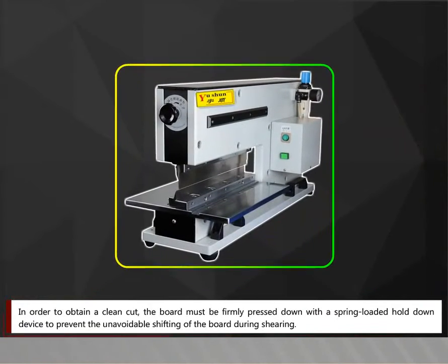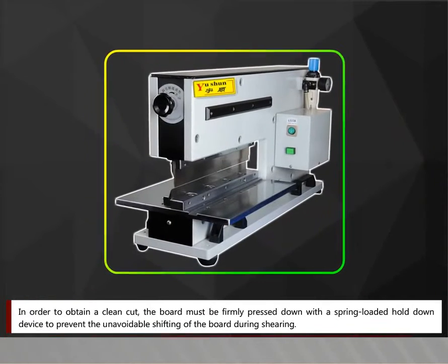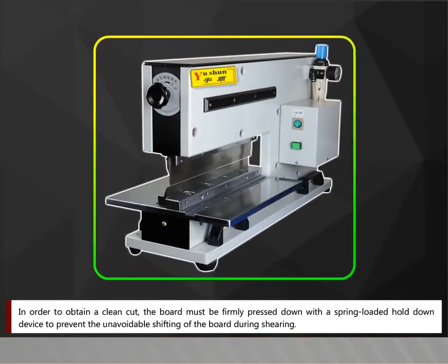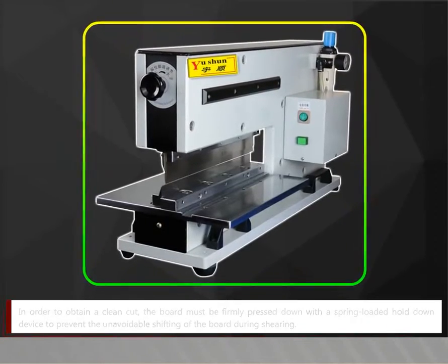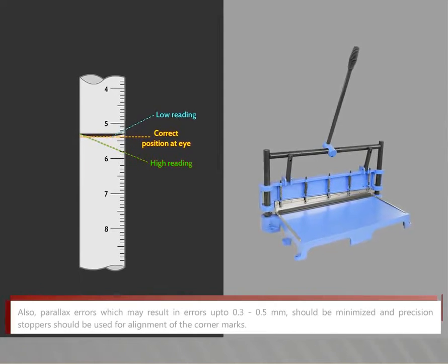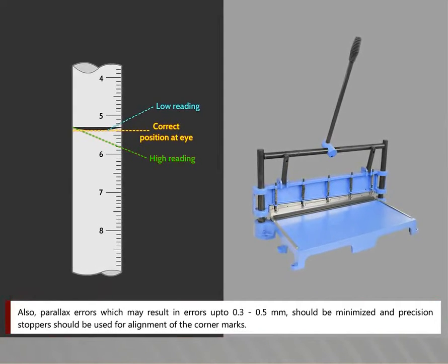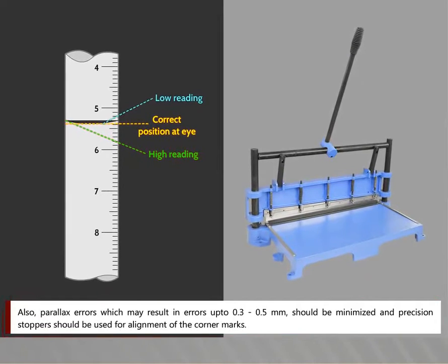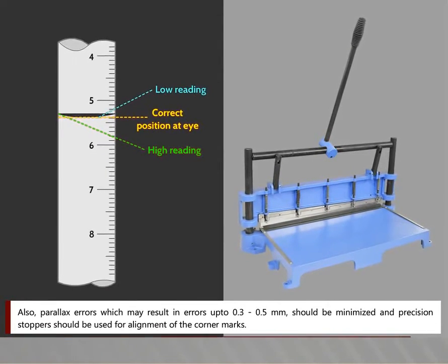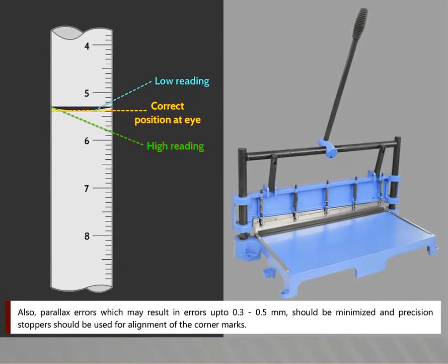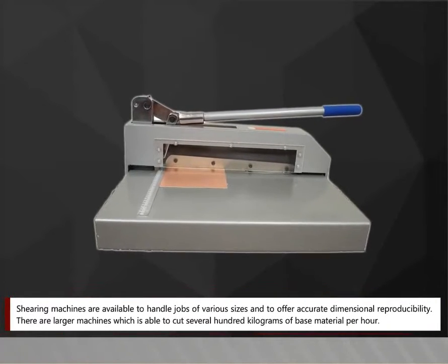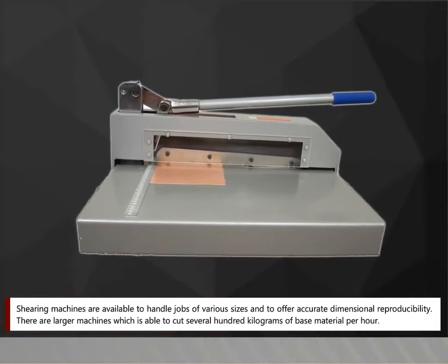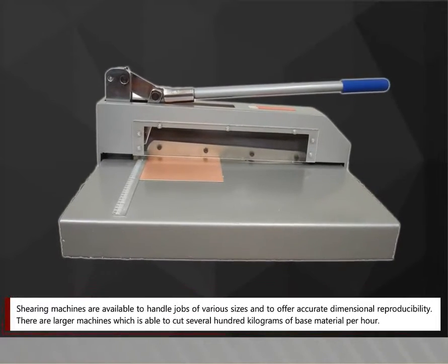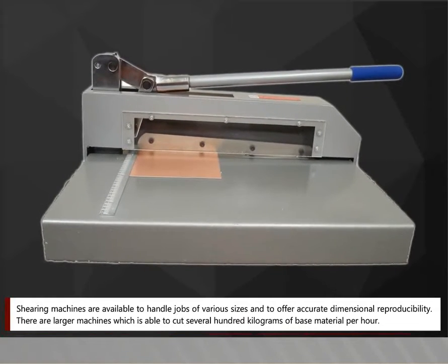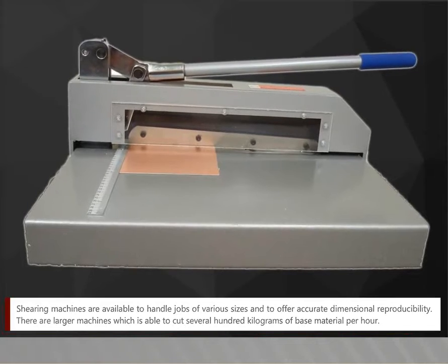In order to obtain a clean cut, the board must be firmly pressed down with a spring-loaded hold-down device to prevent the unavoidable shifting of the board during shearing. Also, parallax errors, which may result in errors up to 0.3 to 0.5 mm, should be minimized, and precision stoppers should be used for alignment of the corner marks. Shearing machines are available to handle jobs of various sizes and to offer accurate dimensional reproducibility. There are larger machines which are able to cut several hundred kilograms of base material per hour.